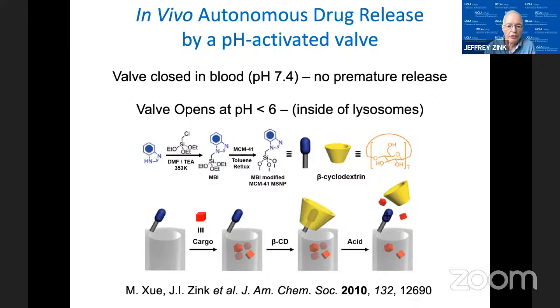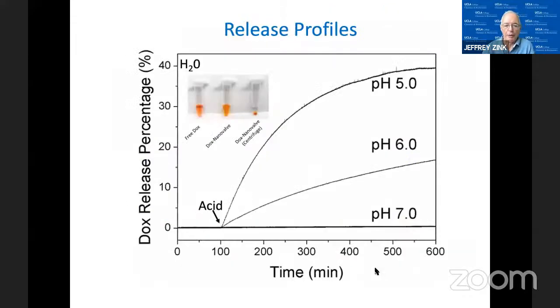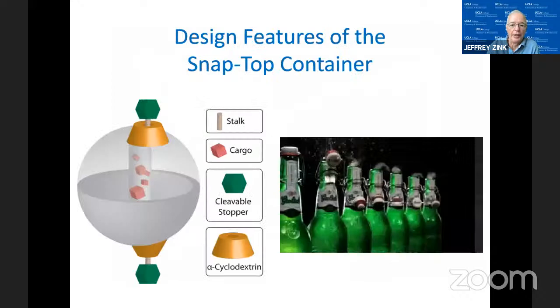But under acidic conditions, you can protonate the nitrogen on the stalk. That makes it hydrophilic. Therefore, the cap comes off, and that can open the pores. So the system works very, very beautifully. At pH 7, the pH of blood, the pores are closed, and no drug molecule, in this case doxorubicin, can come out. As we go towards the pH that occurs in lysosomes and endosomes, 6 and 5, you can see that the system starts to release the doxorubicin because the cyclodextrin caps have come off. So this works very beautifully under physiological pH conditions.